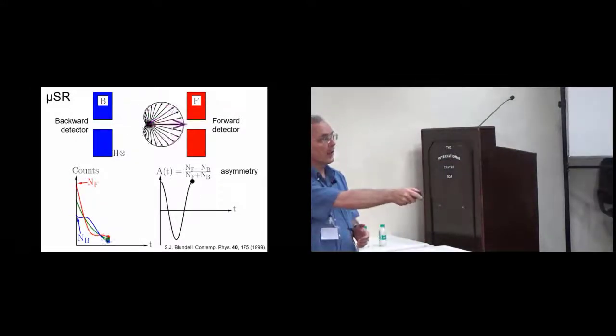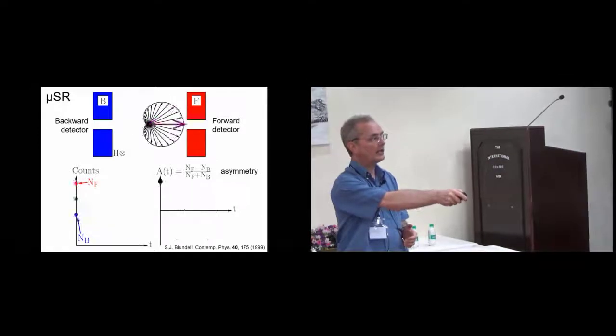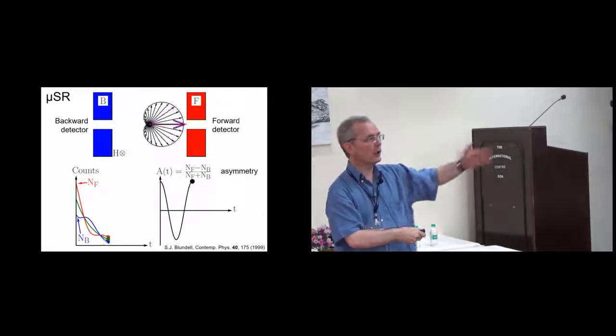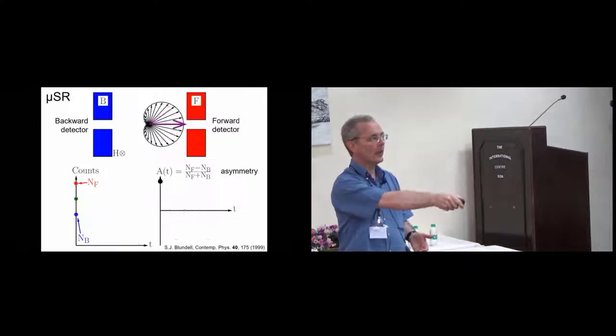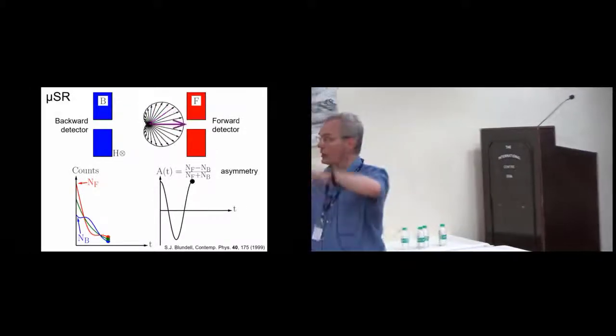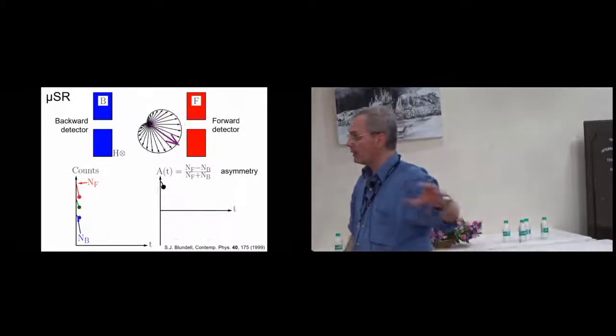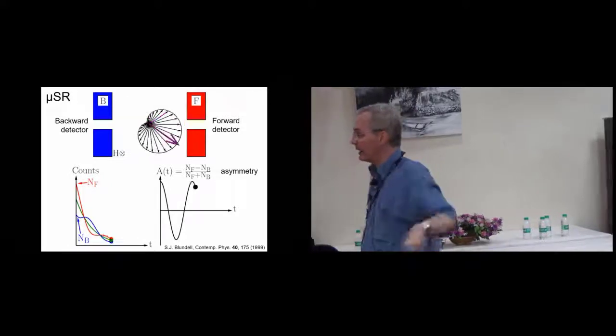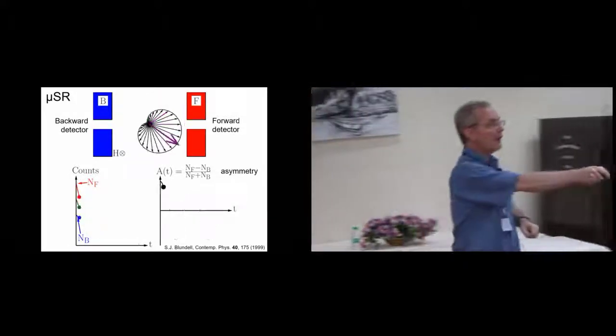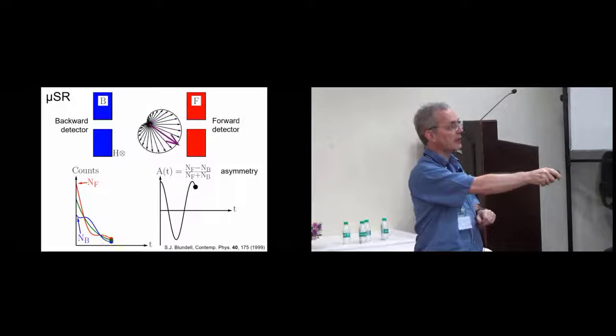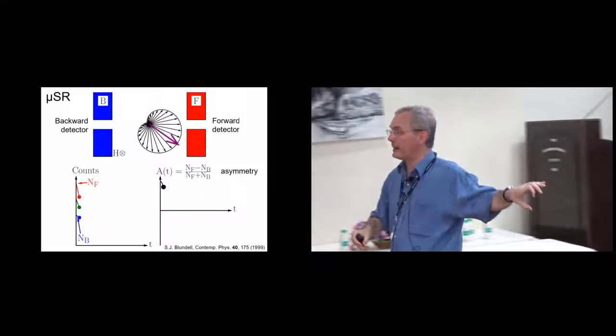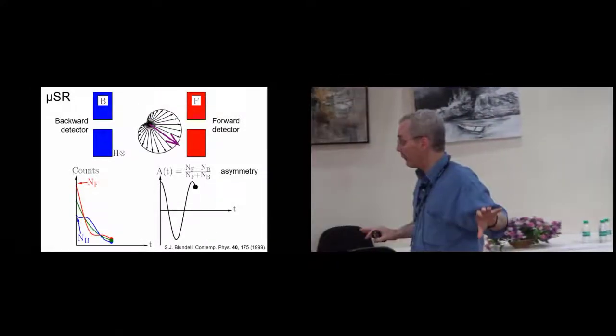And what you can then do is take these curves and subtract the red and the blue curve and divide by the sum, and then you get this curve here, which is just an oscillation. And this is what we generally plot. So this shows you muons precessing in the sample. Now, this has happened because I've applied a magnetic field to the sample. So this is the world's most expensive magnetometer. So this would not be very useful.